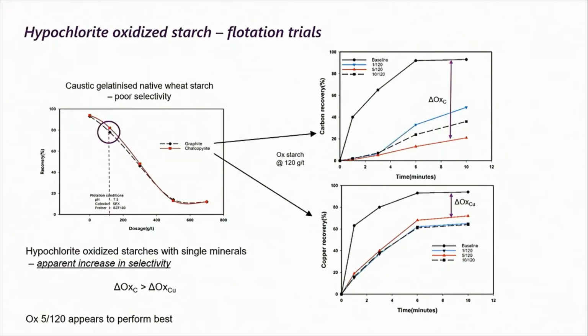So as a first trial, I took some starch and I oxidized it with sodium hypochlorite, just at 3 levels, at 1%, 5% and 10%. And you can see on the left there that I've got a flotation response for just pure graphite and pure chalcopyrite. And you can see that those curves are quite close together, indicating there's not a very great selectivity between the two.